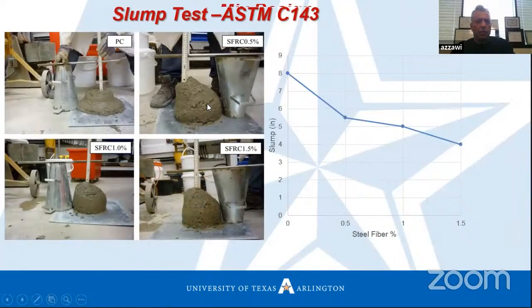Then we start to produce the concrete. First of all, we check the slump. As you see, the slump without any fiber goes to around 8 inches. With 0.5% steel fibers, the slump is reduced, as we see. 1% is reduced more. At 1.5%, the slump is around 4 inches, which I can say is accepted in practical work. Yes, the workability will be tough, but still the strength will be high.